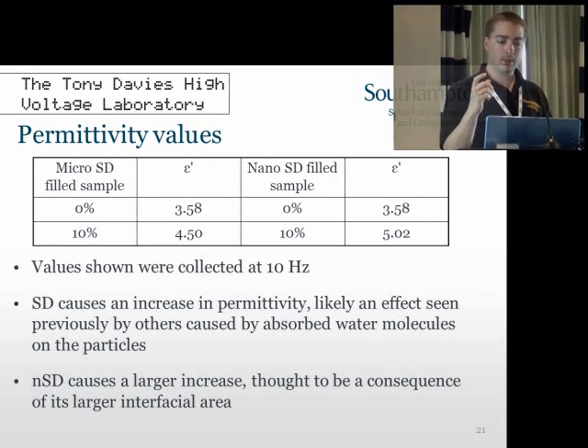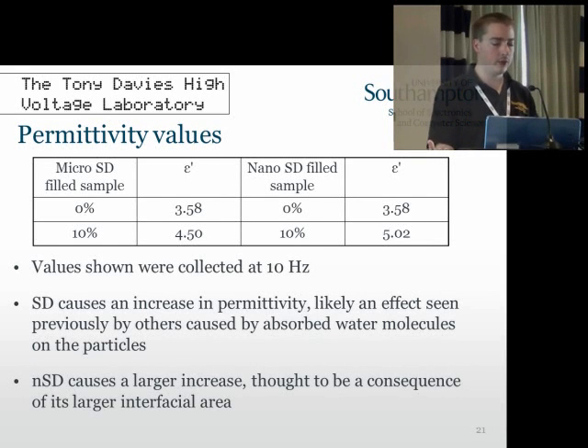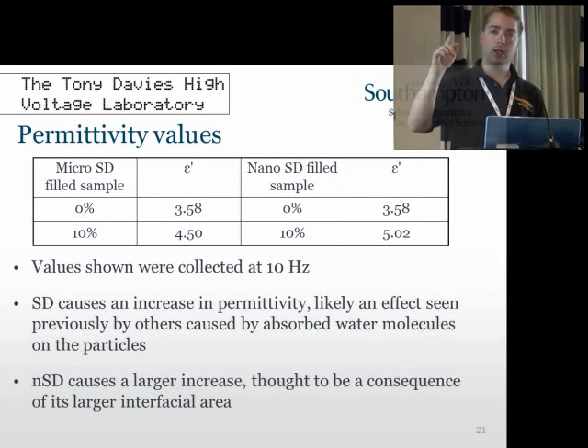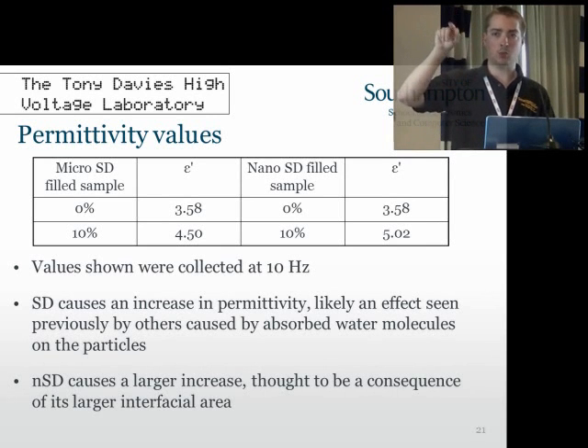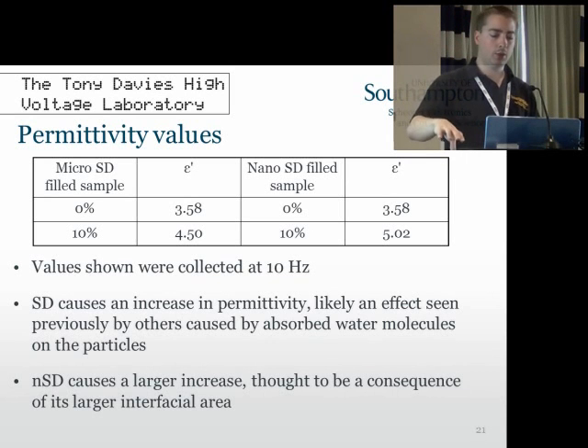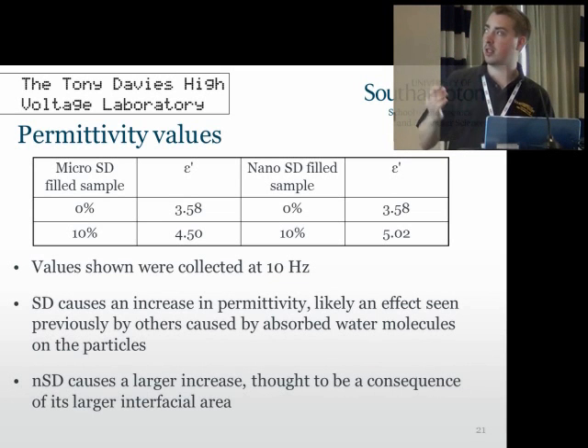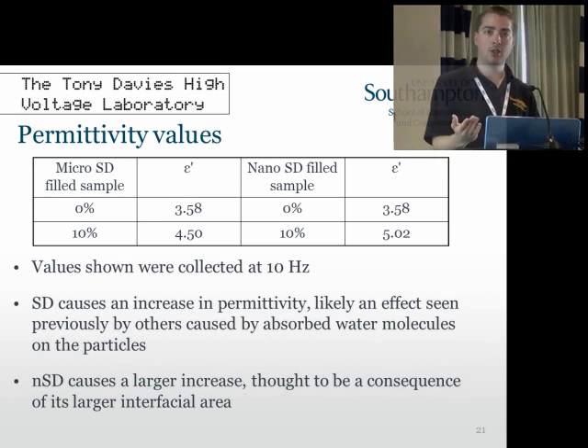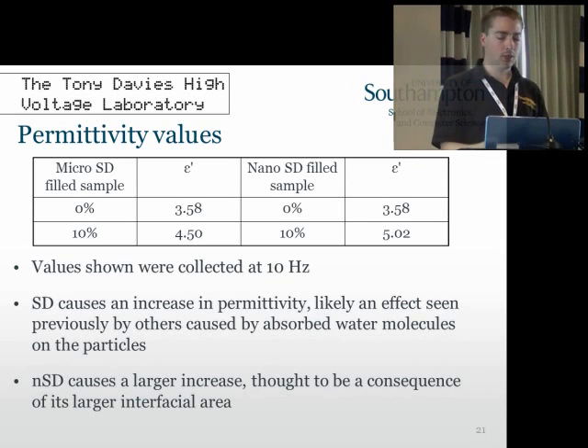Now, having a look at the standard mixing laws, and trying to understand if this would be the case, we've come to a fairly sure conclusion that this water is what's causing a higher permittivity and also the breakdown strength to decrease. So as the breakdown occurs, the jumping between the particles is actually jumping to the water around the edge of the filler, which is causing this increase in permittivity. This also ties in with the fact that the permittivity increase for the nano system is actually higher, so we have more interfacial areas. There's a lot more surface area involved, which means there's going to be a lot more uptake of water holding onto the filler. So it all ties together.